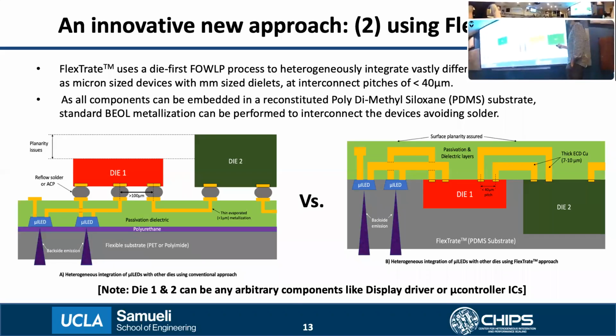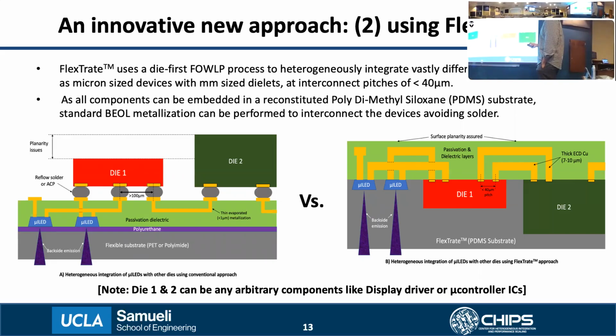The second innovation is our flexible electronic integration approach, which we call FlexTrate, which is a die-first fan-out wafer-level packaging process that allows us to heterogeneously integrate vastly different components, such as micron-sized devices with millimeter-sized dielets, all together in a common reconstituted substrate at very fine interconnect pitches of less than 40 micron.